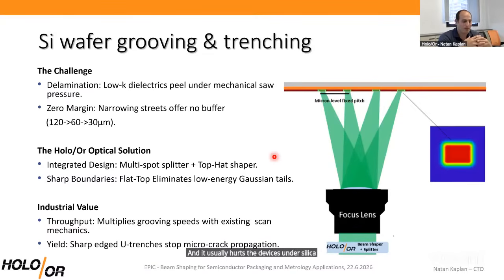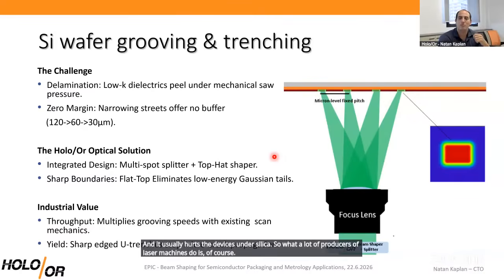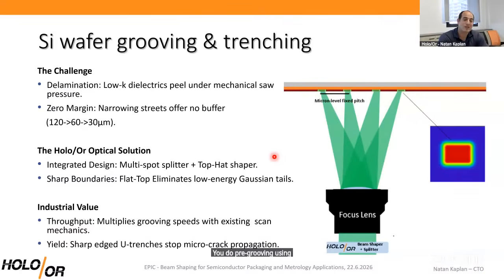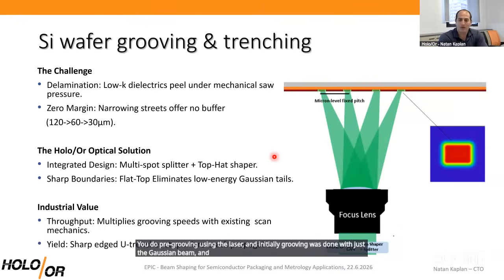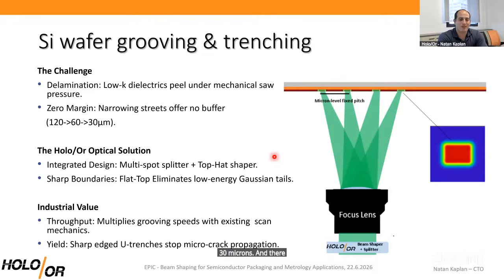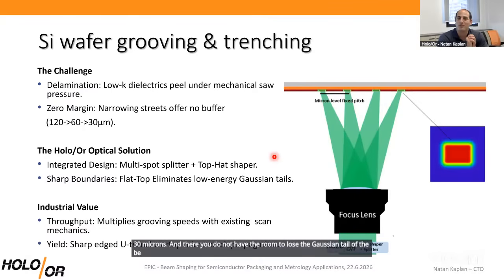So what a lot of producers of laser machines do is, of course, you do pre-grooving using the laser, and initially grooving was done with just the Gaussian beam, and it sort of works, especially for broad streets. Originally, streets were 120 microns, even more sometimes. But as we're moving to denser and denser packaging, streets are becoming narrower, 60 microns, 30 microns. And there you do not have the room to lose. The Gaussian tail of the beam is too destructive.